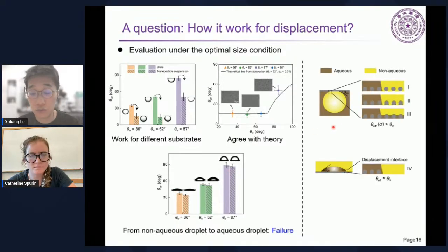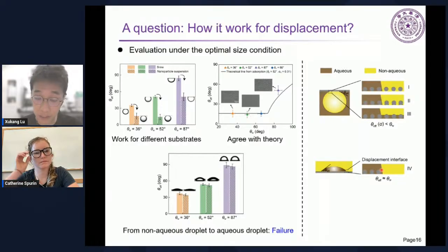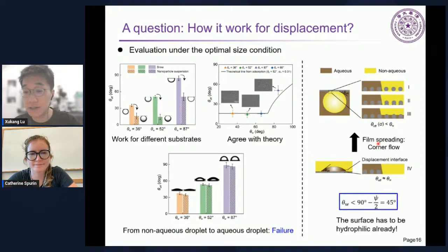And if we look at these 2 phase configurations carefully, the aqueous droplet condition is actually closer to displacement to some extent. So basically we have some regions occupied by the non-aqueous phase, and we want the aqueous phase to enter there. But intuitively, as you can see from this illustration, there's no motivation for these particles to enter there, so their adsorption is basically restricted to the aqueous phase, and the 3-phase contact line is hardly affected. So that's the reason we have this failure. And so the next question is, does that mean nanoparticles cannot help multiphase displacement? Of course the answer is no, otherwise we wouldn't have the next part. But the key factor here is that we need some pre-film spreading to drive particles to enter there and then further change the local wettability.